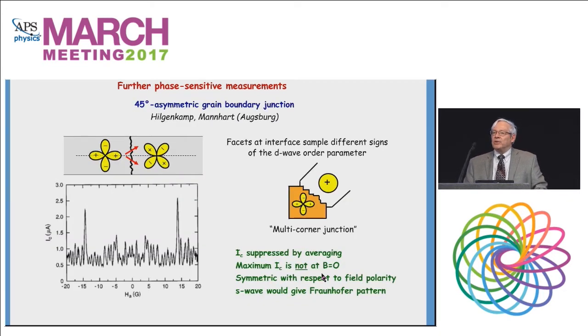Another nice experiment was a grain boundary junction. If you make a junction where the lobe of the order parameter points into the node, you would like to think that the critical current would go to zero, but that's not what happens. What happens is you have facets along the junction, so the current actually alternately goes in different directions, and you get what looks like a multiple corner junction experiment, and you get these very characteristic patterns, which are characterized by a lot of modulations, critical current which is maximum someplace other than zero magnetic field, and it's highly symmetric with respect to field polarity. If you had an S-wave superconductor, this junction would give an enormous critical current at zero field.